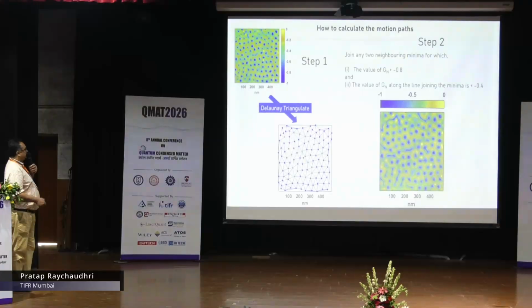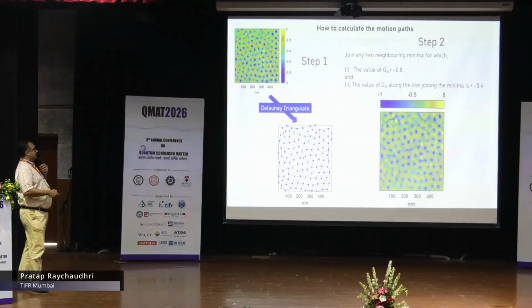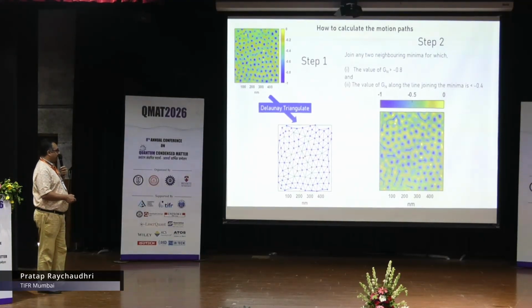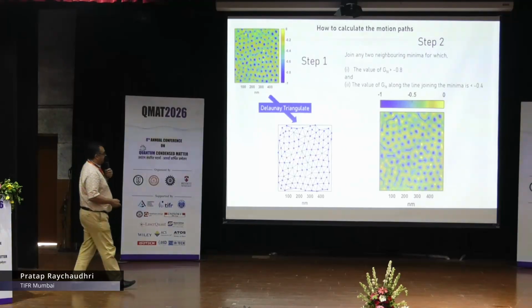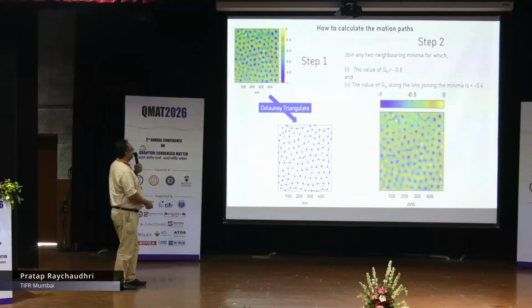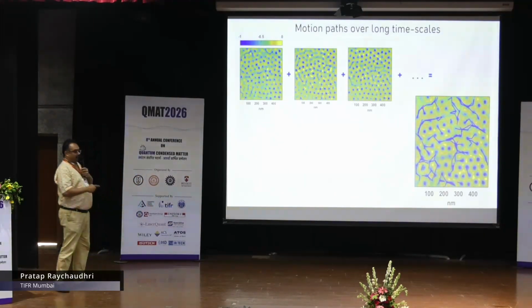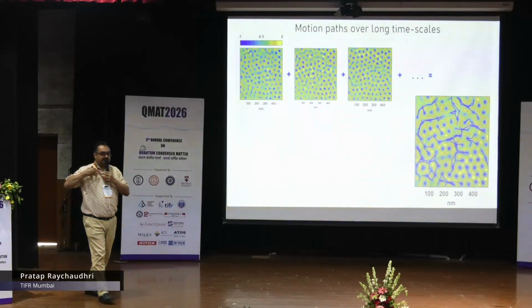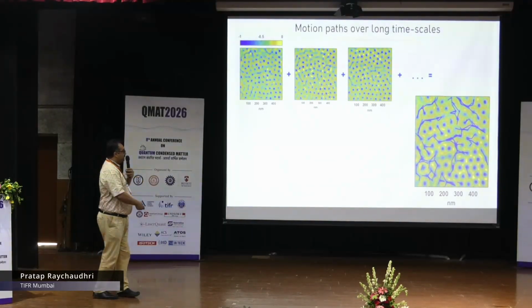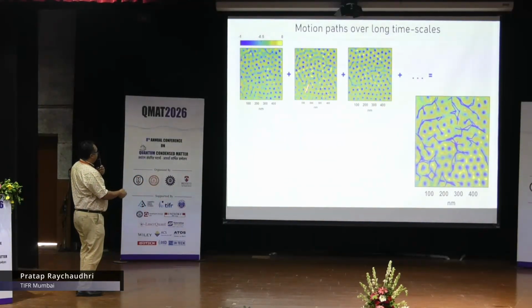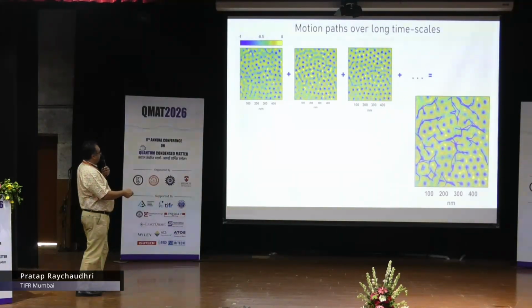So you first find the minima, you find the nearest neighbor by Delaunay triangulation, you use some criteria and find the motion paths where these vortices are moving. However, we don't do this experiment once. We don't take one image, but we take a series of 10 or 20 images. And when we do this analysis for every frame, we see that this motion path changes with time.